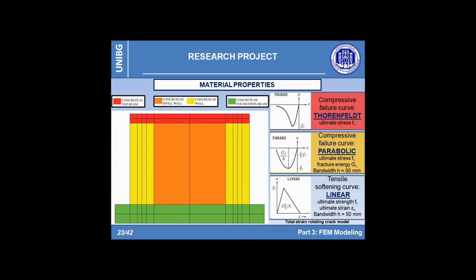Regarding the compressive behavior for the fiber-reinforced sprayed concrete, the parabolic stress-strain diagram model was used. In the latter, the data input corresponds to the ultimate stress and to the compressive fracture energy. To describe the compressive behavior of the ordinary concrete, instead, the Thorenfeldt model has been chosen, defining only the maximum compression stress.